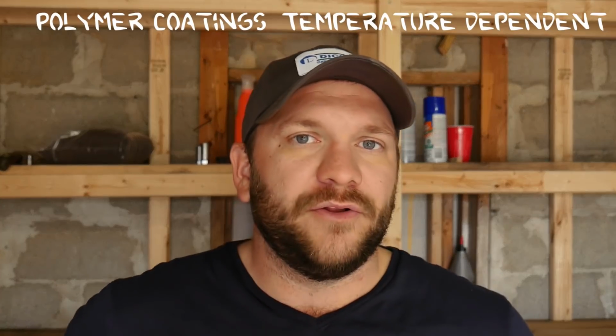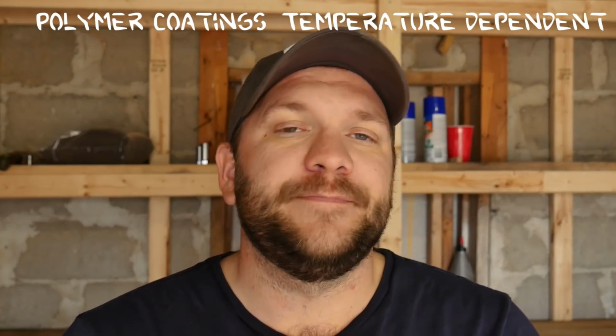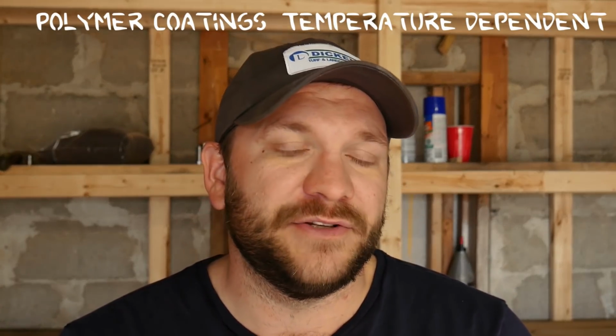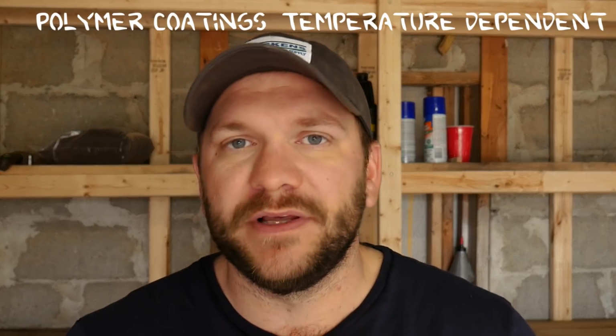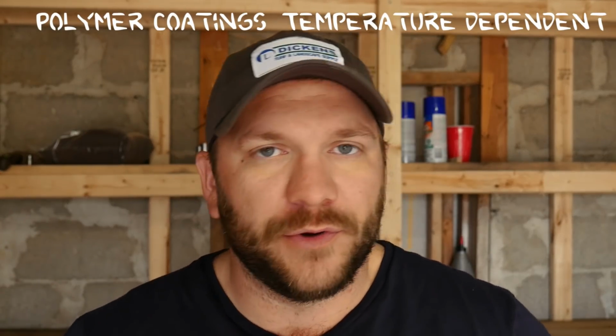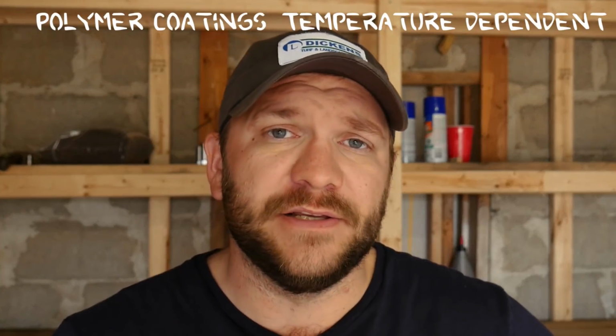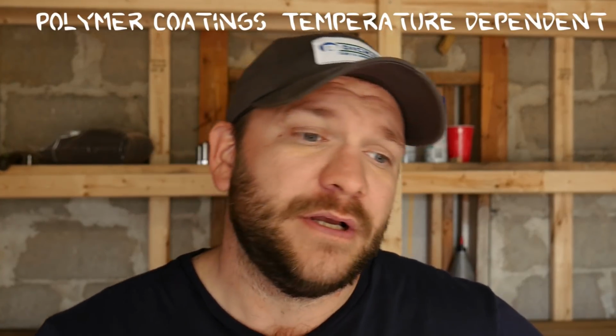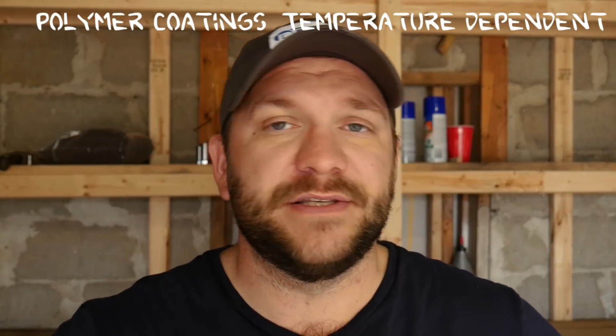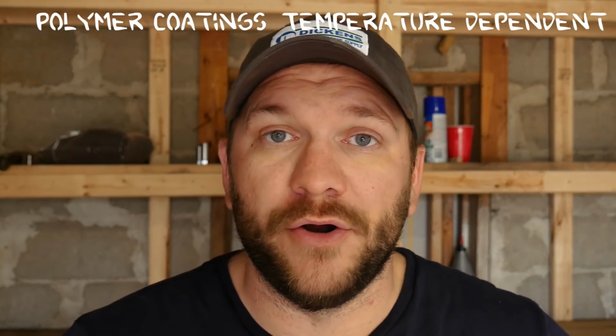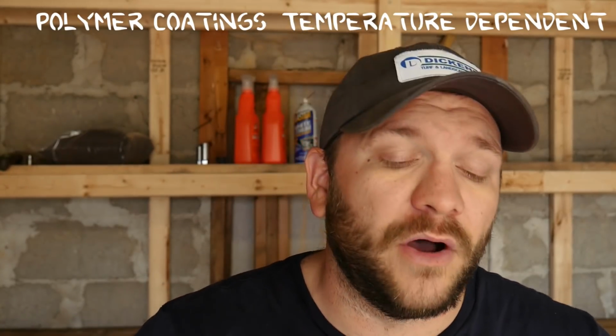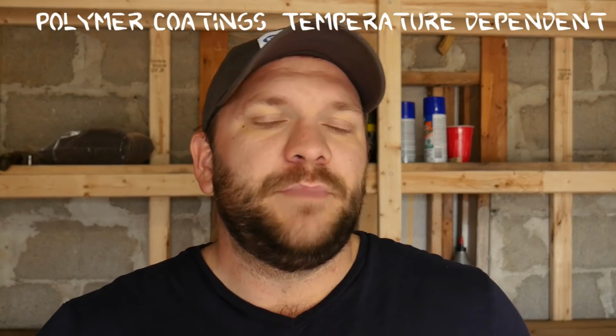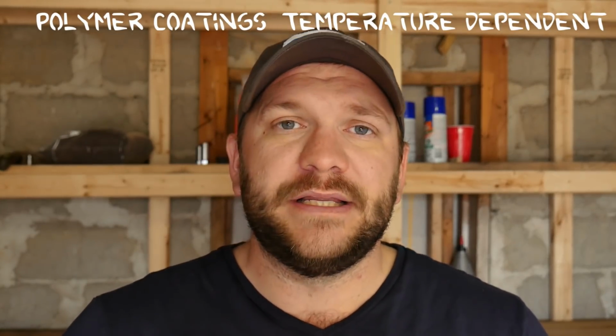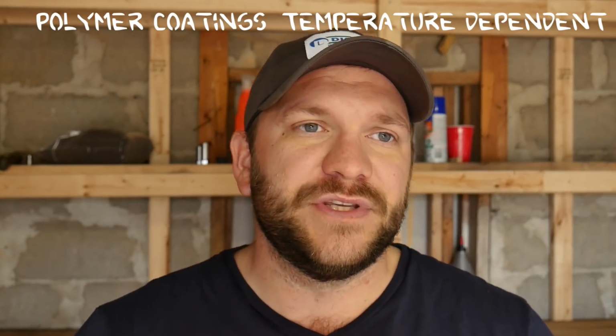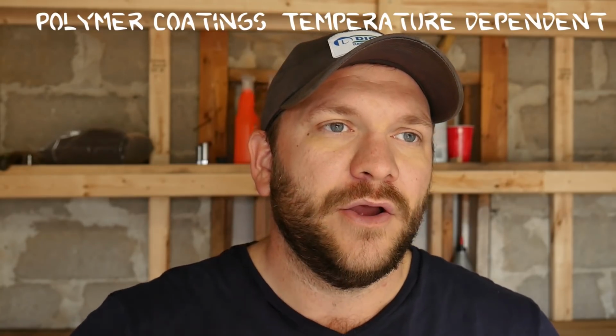One thing in particular that I've run into an issue with using a polymer coated technology is a huge release on weeks of 100-degree weather on cool season grass, and it's led to significant amounts of drought stress and then ultimately burn or kill areas of the lawn. So polymer technology is good, but you have to understand where to use it as a tool. You have to understand where to use it as a turf type.